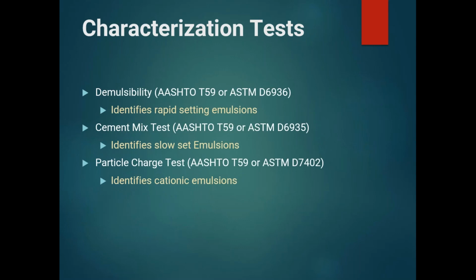Some of the very common characterization tests are demulsibility. You may hear this called demulse. This test is used to identify rapid setting emulsions. Basically, you take a soap of the opposite charge of your emulsion. So if you're testing a cationic emulsion, you'll have an anionic soap, and you mix that together and look for a certain amount of that emulsion to break out. And by each of these tests, I've also listed the AASHTO or ASTM procedures, so you can go back and read more about these later if you want to know more about how the test is run.